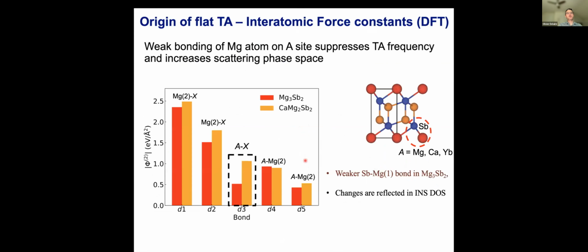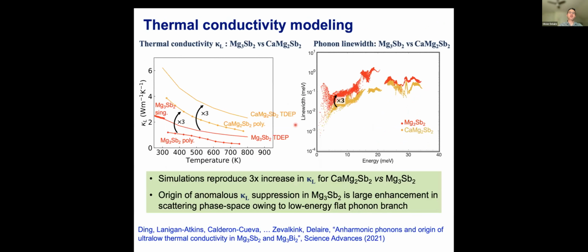And so the student Jingshuan did a really fantastic job in really extracting which interatomic force constants are impacted by this substitution between magnesium and calcium, and found a very large effect in a specific bond that connects the magnesium 1 site with the antimony site here. And so based on this modulation of the phonon dispersions, you can really understand the phonon scattering phase space. Predictions of the line widths here are also increased by a factor of 3 when you go from the binary to the ternary, which is again very surprising, but matches very well what is observed in the measured thermal conductivity.